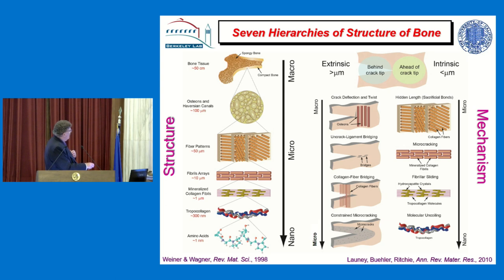But if we go above about a micron and look behind the crack tip, bone looks like a ceramic. We get lots of micro cracks, which play a role, but a little bit more complicated. Each one of these micro cracks has these fibrils that bridge the crack, like fibers in a composite. There are little regions between the micro cracks, which give you resistance to fracture, and the cracks can deflect when they hit these osteons, which are the ones I talked about. They run along the axis of the bone. So your arm is easy to split. You can easily split your arm, more difficult to break it, because when you break it, your cracks are hitting these osteons and they deflect, because there's a little bit of mineral along the axis of those osteons.